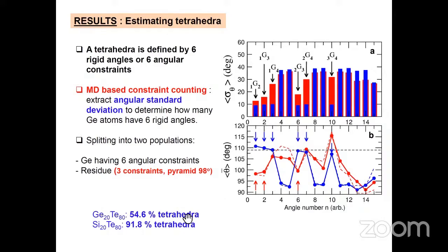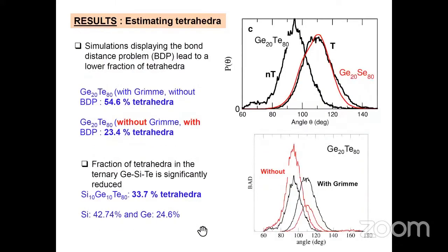And now we can evaluate those numbers, and we detect that in GeTe, we have more than 50% of tetrahedra and about 90% for the corresponding silicon telluride. Now we can also plot the corresponding bond angle distribution, and we find for the same system a first distribution which is indeed centered at 109 degrees, the tetrahedral angle, which is very close to the one which you would calculate for the corresponding selenide. And then you have a residue, which is the one centered at 98 degrees.